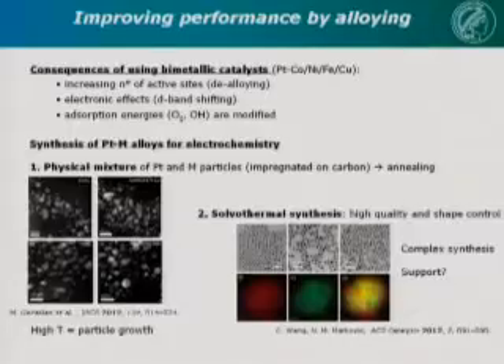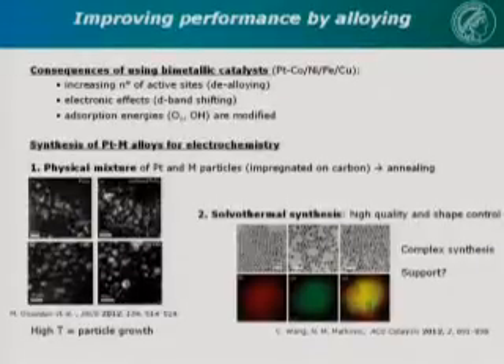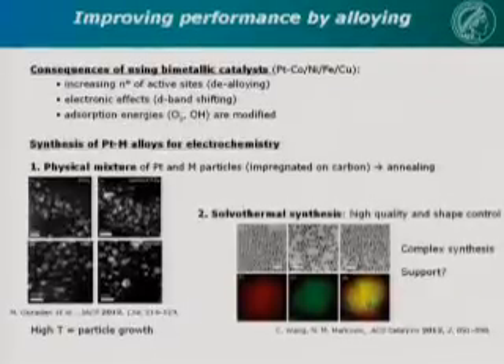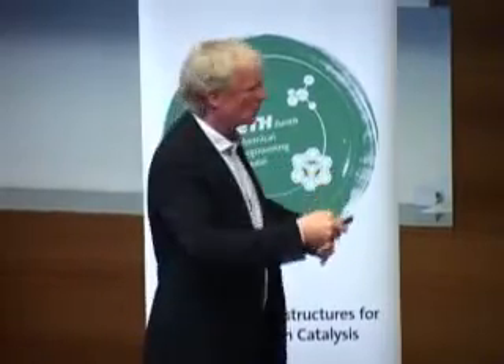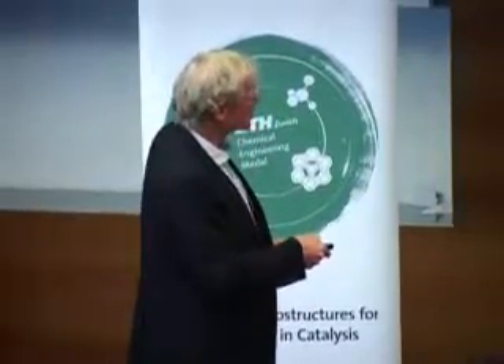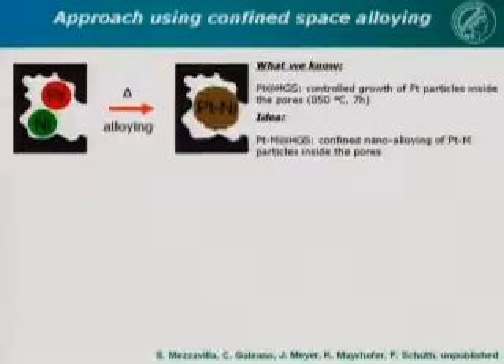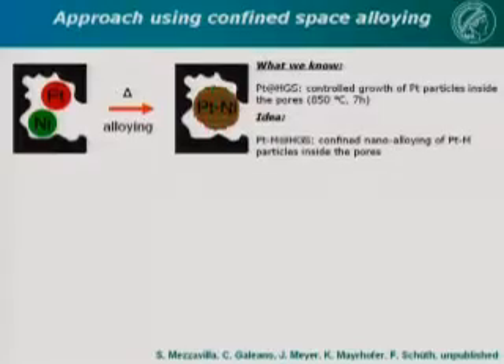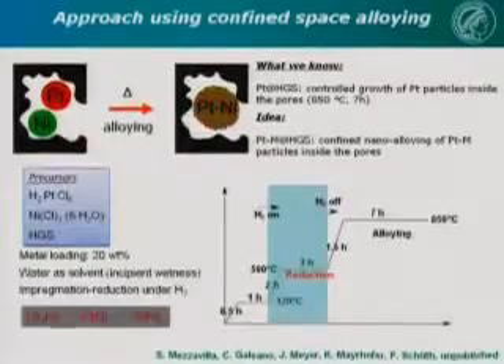The other possibility is first synthesize in solution the alloy particles, then deposit them on a support. But this is also not very good because you cannot nicely anchor these preformed particles on a support. And then again, Carolina and Stefano Mezzavilla had the idea, well, why don't we use these hollow graphitic spheres, the pores in the hollow graphitic spheres, as confining geometries to produce alloys on the nanometer scale? So if we fill one of these pores with nickel and platinum, we can heat it to form the alloy, but at the same time prevent growth because they're confined in these 4 nanometer pores. That was the idea behind it.